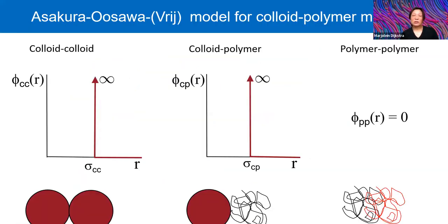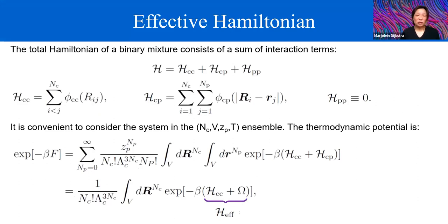And so a very simple model that was introduced by Asakura and Oosawa is called the Asakura-Oosawa model. In this model, the colloids are treated as hard spheres. The colloid-polymer interaction is also treated as a hard-sphere-like potential, and the polymer-polymer interaction is treated as an ideal gas. So the polymer-polymer interactions are basically set to zero because the polymer coils can overlap with each other. And for this very simple system, the total Hamiltonian of this binary mixture consists of a sum of interaction terms, the colloid-colloid and the colloid-polymer interaction terms.